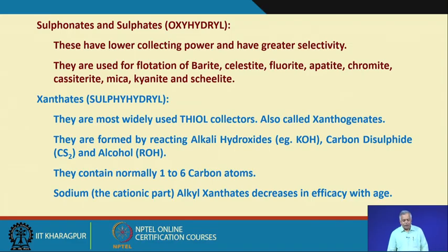Another example is sulfonates and sulfates. These are called the oxyhydryl collectors. These have lower collecting power and have greater selectivity. That means it can sit selectively onto your targeted mineral surfaces, but its collecting power is very low, because the bonding may be weak.